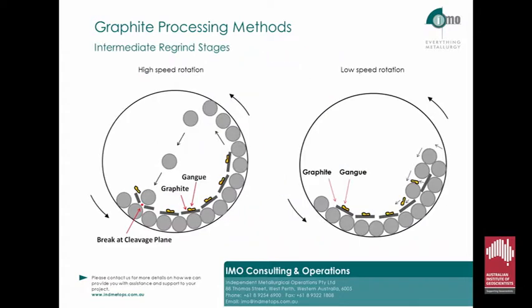The regrind stages are what I've found to be most important in achieving a high-grade concentrate with good flake distribution. The picture on the left shows a typical mill which lifts the media, generally either rods or balls, and drops them onto the ore. However, this is not what we want, as it can reduce the amount of flake. What we do want is shown on the right side of the slide, which is to have the media essentially roll over the graphite particles and liberate the flake from the graphite flake edges, purifying the graphite. As I mentioned previously, having soft gangue minerals is advantageous in this stage, as less energy has to be applied to liberate the flake, reducing the chances of breaking the flake.